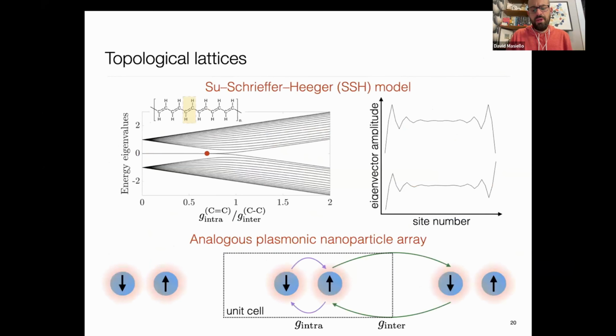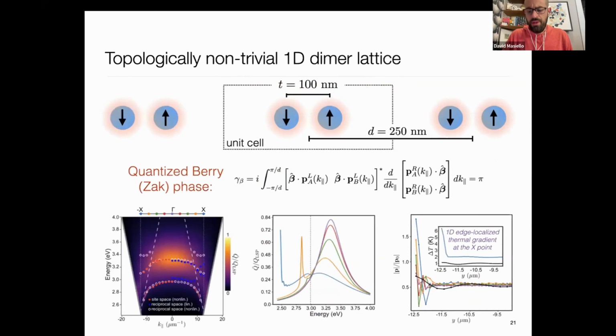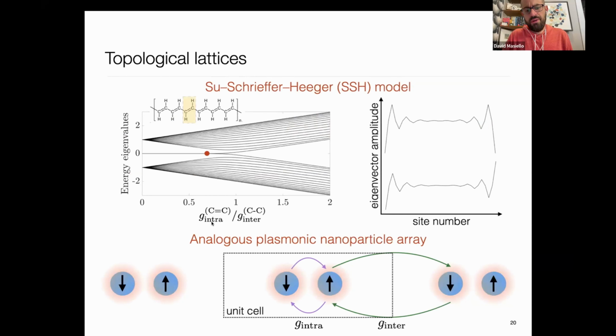So the last part of the talk, in the last 2 minutes, I want to just turn over to some of the topological effects that we anticipate in these kinds of structures. And I want to go back to the model of Su-Schrieffer-Heeger, the so-called SSH model, which is a prototypical model for topological effects. The model describes a charge hopping, a spinless electron hopping along polyacetylene, and where as a function of the carbon-carbon double bond hopping rate to the carbon-carbon single bond hopping rate, what you're looking at here is the eigenspectrum of a finite piece of polyacetylene. And so what you see here is that when this ratio crosses one, and the inter-unit cell hopping rate exceeds that of the intra-unit cell hopping rate, then two states coalesce at zero energy.